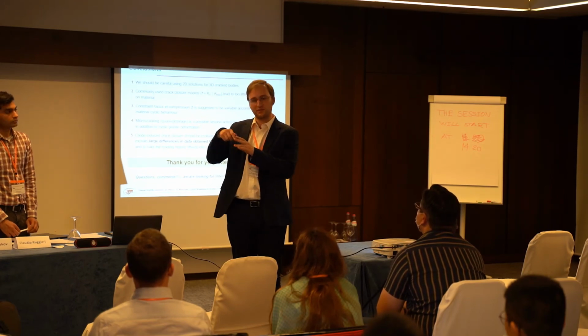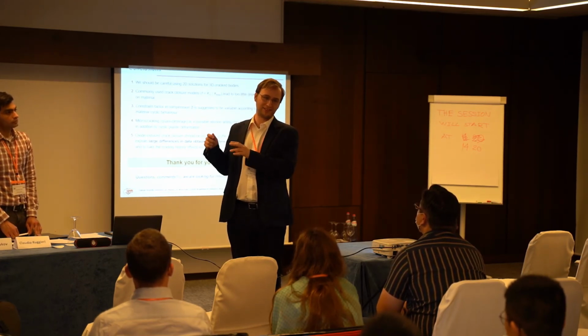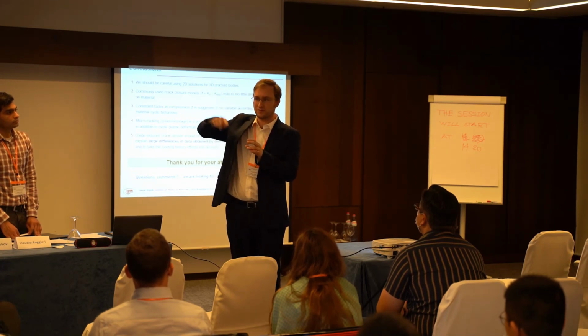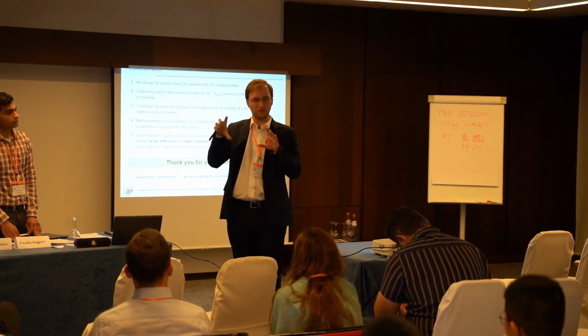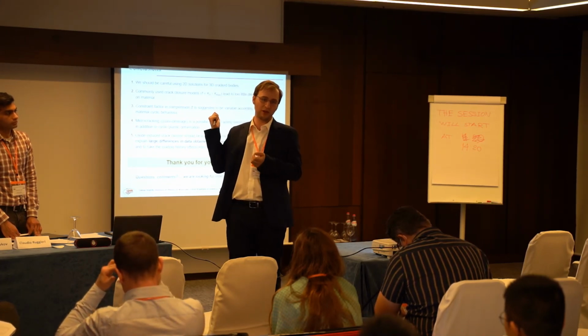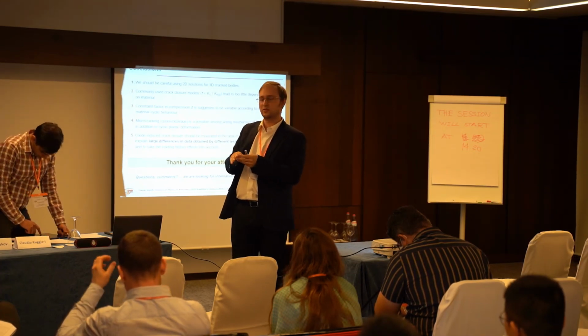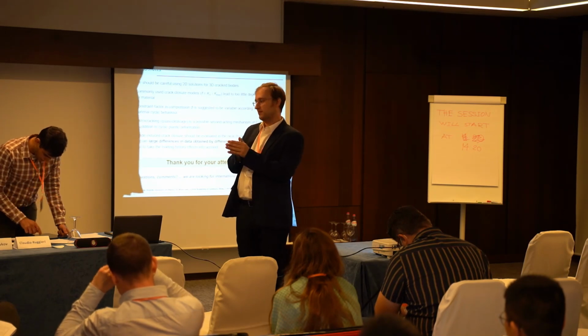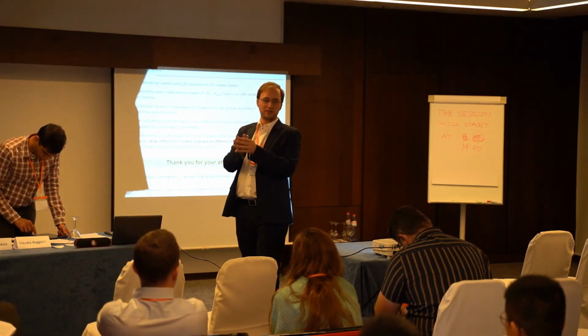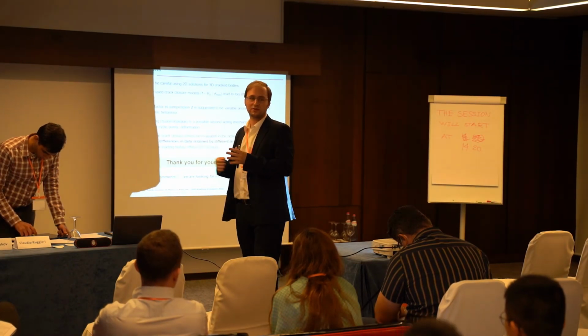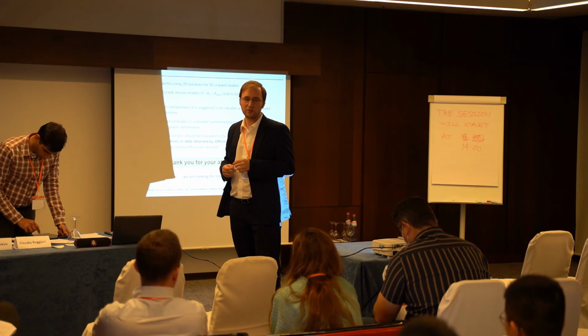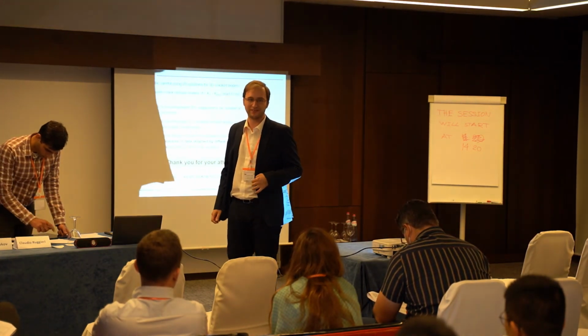I think this is a question of whether we have good quality modeling of the effects of overload and underload regarding plasticity. There will be an effect if we have random cycles in time, or if we have a block of small, block of large. There will be a difference if we use different models, so that would be a problem. Regarding oxide-induced crack closure, we have a model where at each cycle, the oxide layer grows a little bit, but then the crack propagates away from it. So if we get the correct crack growth rate, we also have the correct influence of oxides. So this would be rather a problem of the plasticity-induced crack closure model. Thank you.